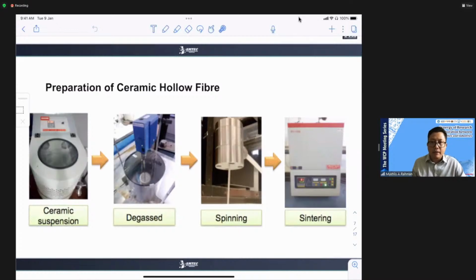In the spinning process, we use a spinning system with a spinneret. This spinneret, in the center, consists of a needle that we use to pump water in the middle, the lumen, to carve the lumen. After this process, we immerse all this precursor for about 1 day, until all the polymer is frozen, and then we take out the precursor, straighten, cut them, and dry before sintering at high temperature. The sintering process is required to burn off all the polymer binder, the dispersant, and organic solvent. So in the end, we get a pristine ceramic hollow fiber.